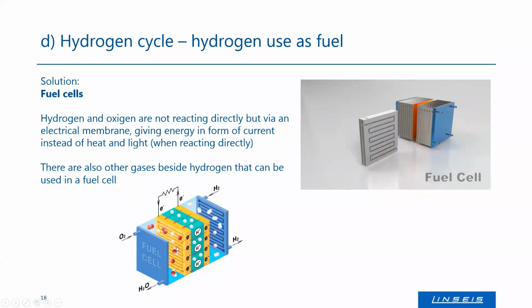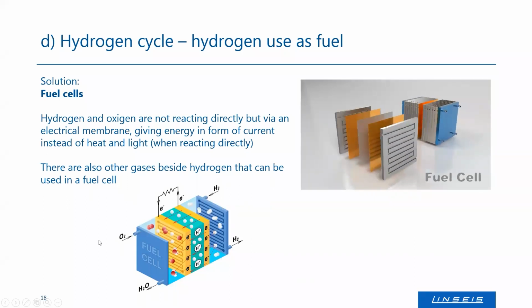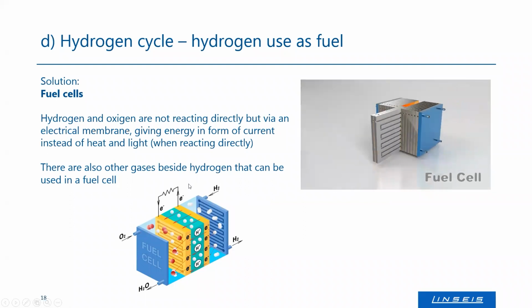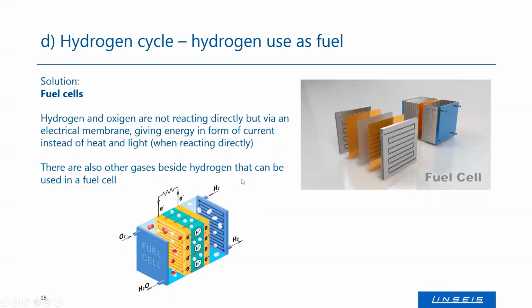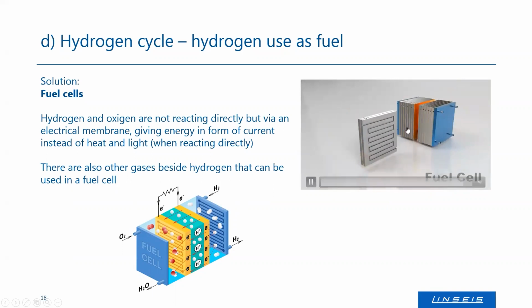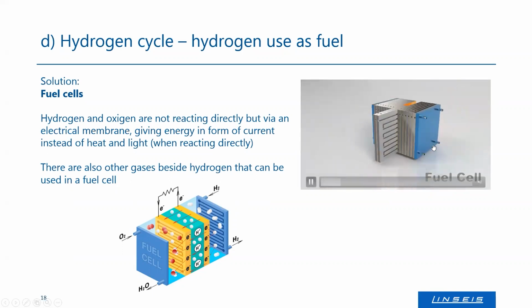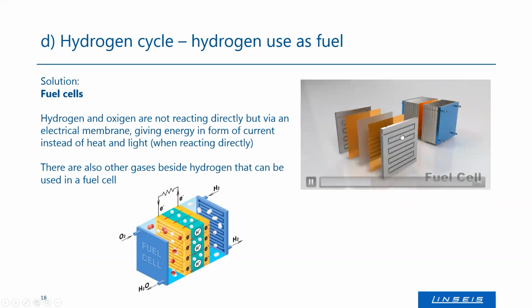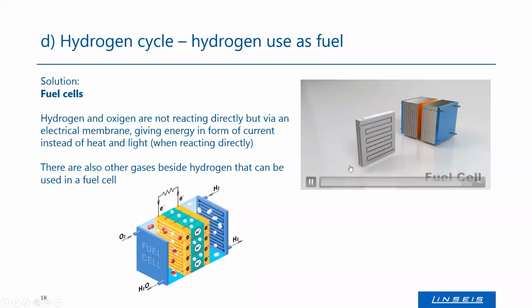This is a controlled reaction between hydrogen and oxygen. It's not just burning off, it's really a controlled surface-bound reaction, providing a very high amount of energy out of that. Almost all the energy can be taken out of that. It's a quite known process and a quite optimized process. On the video over here, you see how the typical setup of a fuel cell looks like. And these fuel cells are already used in hydrogen-driven trucks, hydrogen-driven buses, and so on.